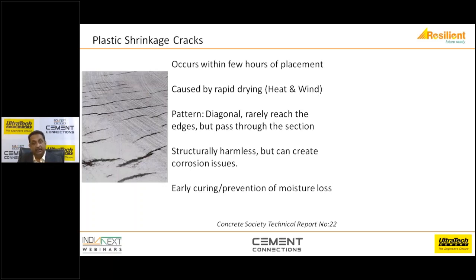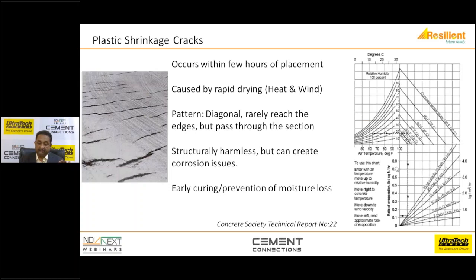So the best way you can prevent this is to start early curing. And when you do early curing, how early is early? You need to make sure that when the sheen on the concrete is off and it starts looking a little bit dull, that means you have started losing moisture from the surface. That is when you need to start sprinkling water, or cover with a plastic cover, so that you prevent the moisture loss. There is a very good graph which is again given in the Concrete Society technical report, which tells you when you need to be careful, or what precautions you need to take.